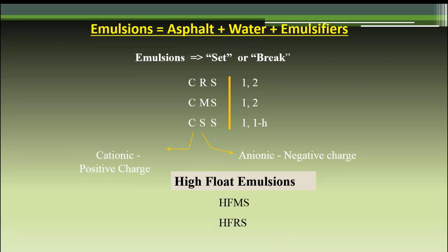And then, as you see there, high float medium set, high float rapid set. You can also see an alpha suffix, and again, that's the modification of the residual asphalt. Rubberized, polymer, latex modified. So as I mentioned, for chip seals across the Dakotas, a lot of times you'll see a CRS, cationic rapid set, 2, viscosity range 2, P, polymer modified, CRS2P.